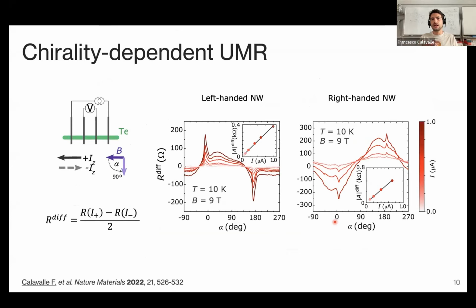Basically, unlike in a Rashba system, where we have a perfect sine typically, because we basically have a circle, here we have a 3D egg, which doesn't have efficiency in all directions, but in principle we have the possibility of converting spin to charge in all directions in tellurium, because all the symmetries are broken. So, I think because of inhomogeneity of the current direction, and also because the sample is not completely ideal, we have these spikes, which are obviously more prominent when the field is parallel to the current, because we have the maximum efficiency.